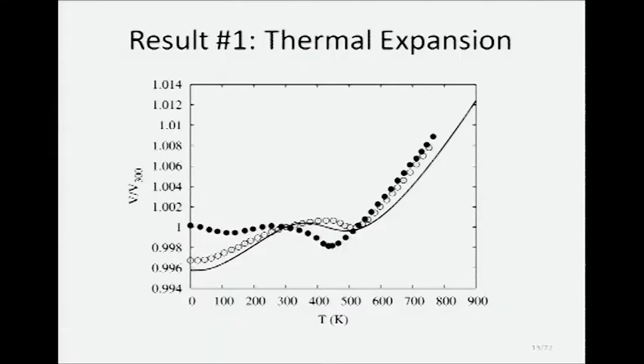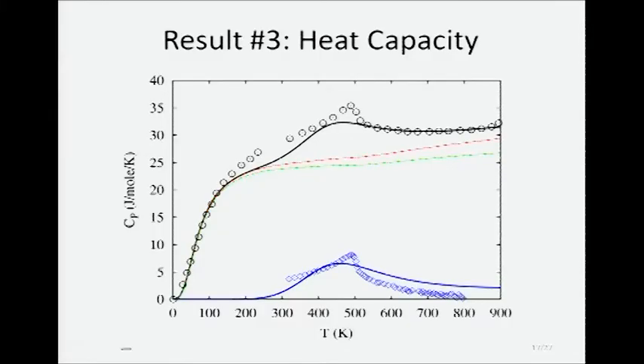The model is based on first principle calculations. Of course, this vibration term I determined by lattice vibration, using the Debye model. Here, compared to experiment, you see negative thermal expansion is precisely predicted. Here is showing the linear thermal expansion coefficient. Here showing the magnetic heat capacity.